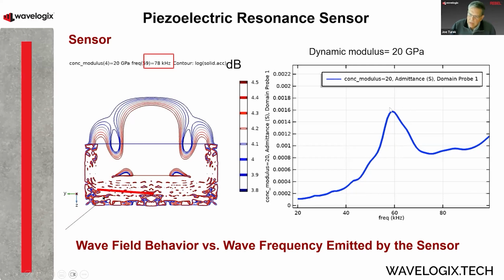Now, what's so interesting about that peak? Well, for number one, we found that peak non-destructively. We didn't have to crush a cylinder. We see that peak. But that resonant frequency of that structure is proportional to the modulus of the structure, and the modulus is proportional to the compressive strength. So by knowing this point of the resonant frequency, we can determine the compressive strength in real time without a destructive process.